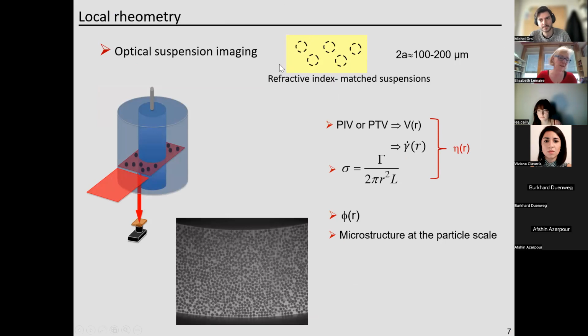We have several systems. One is with PMMA particles. It's much easier than with, for instance, polystyrene particles. With PMMA particles, you can match both the density and the refractive index. You can use a Cargille oil. Cargille is an American company that makes refractive index liquids, and they have also developed a refractive index liquid that also matches the density of the PMMA particles. And you can also just mix Triton X100 and water and zinc chloride, and then you obtain a liquid that is matched both in refractive index and in density.